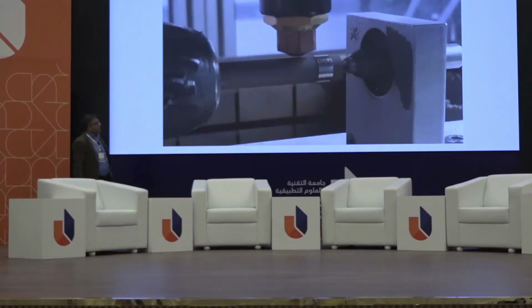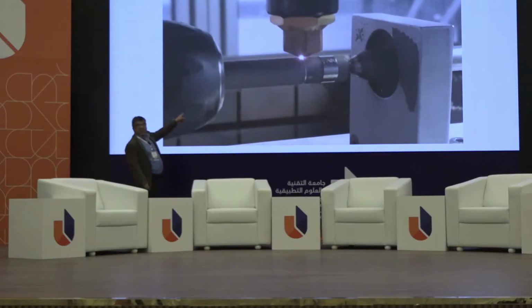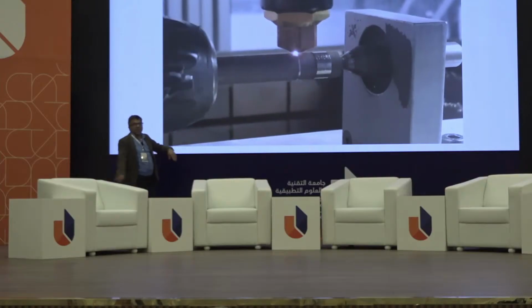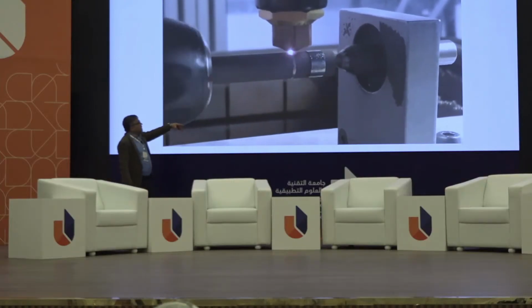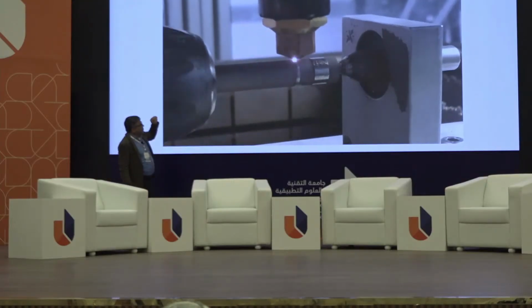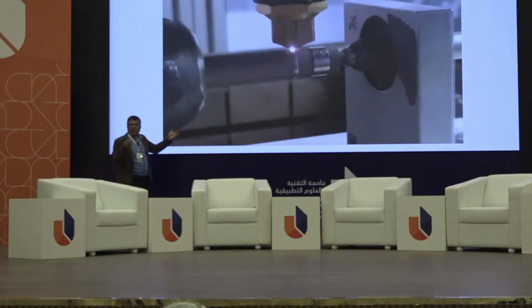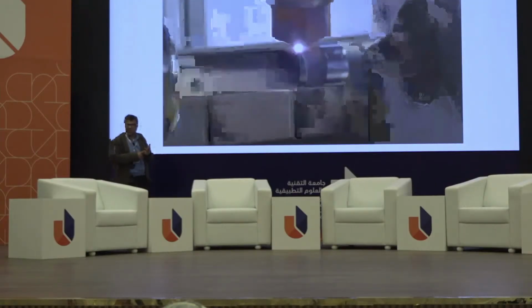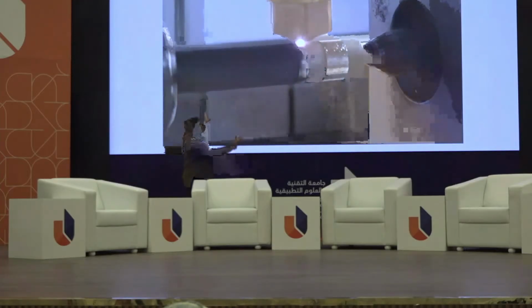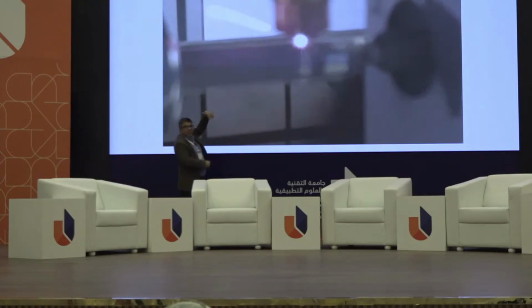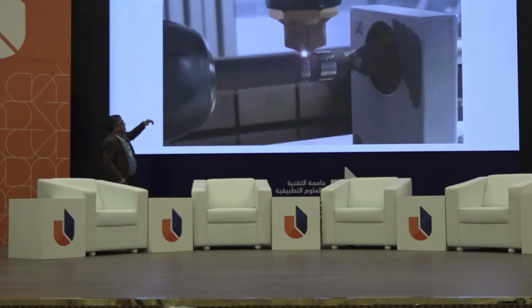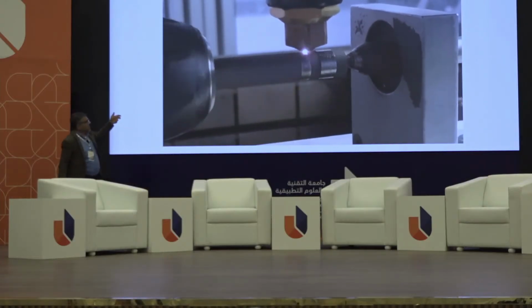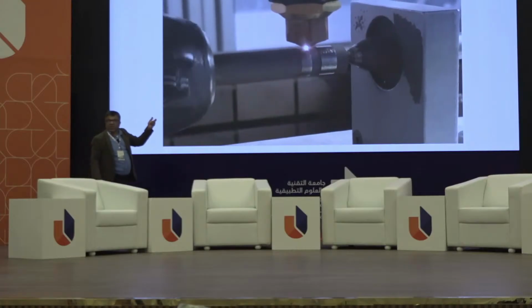The process is here. So this is a different laser. So that's after printing. We finished with the printing. And here I'm polishing. The processing parameters here, of course, the laser power, how much power output, the scanning speed, which is rotational and linear. The sample is made from left to right, and the laser beam is fixed. So the laser power, rotational speed, linear speed,